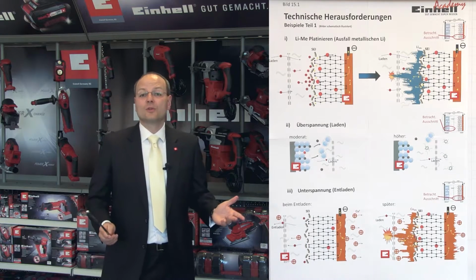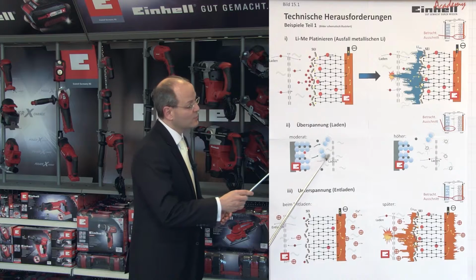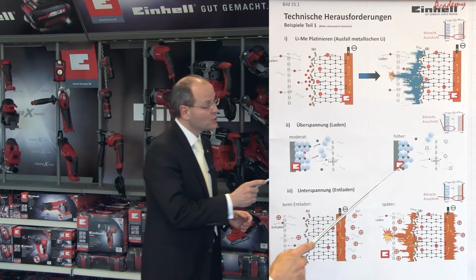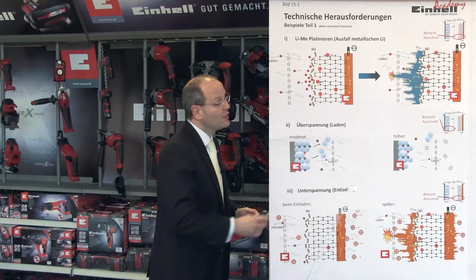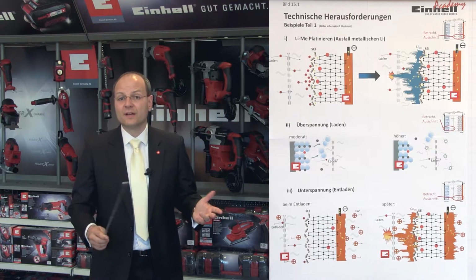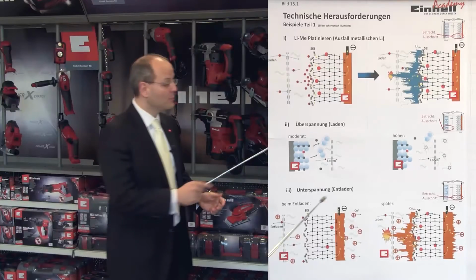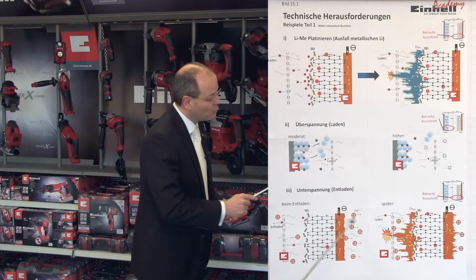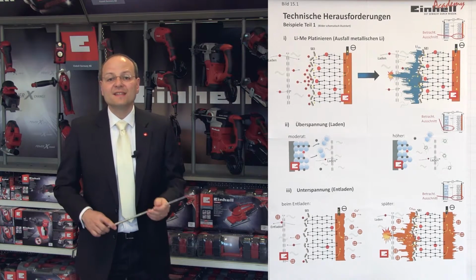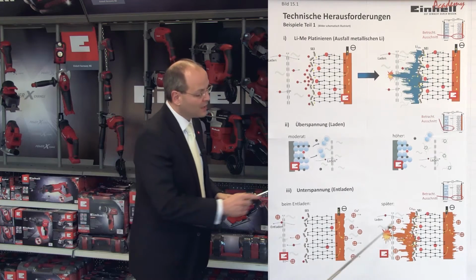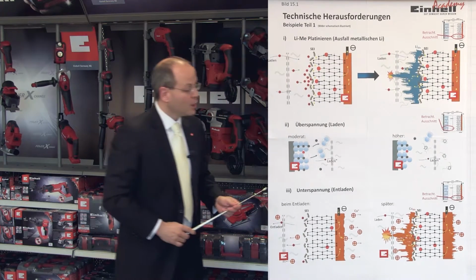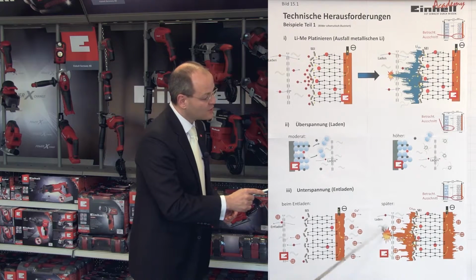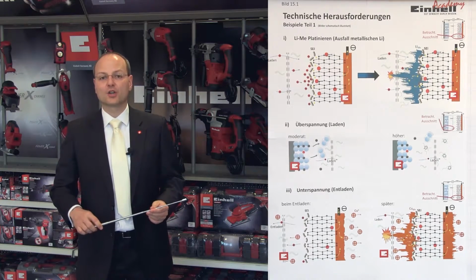If the voltages between the electrodes are too high, the cathode material breaks up under release of oxygen. In addition, the organic solvent disintegrates electrolytically under release of gases, some of which are highly explosive. Likewise, if the voltage differences between the electrodes are too low, a situation known as deep discharging, degenerative chemical reactions take place in which explosive gases can be released. In addition, metals from the anode base, usually copper, can dissolve in the electrolyte. During the next charging process, these grow into needle-shaped structures on the surfaces in a similar mechanism described for lithium. If these needles penetrate through the separator, this results in severe internal short circuits in the cell, so-called hard shorts.